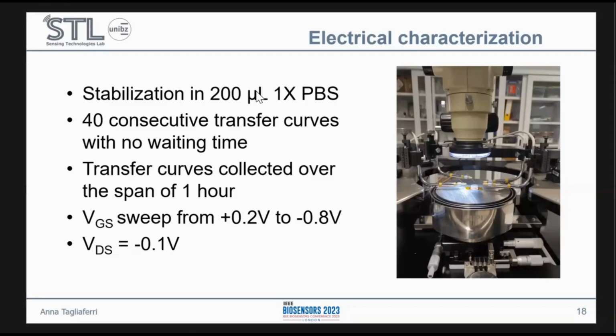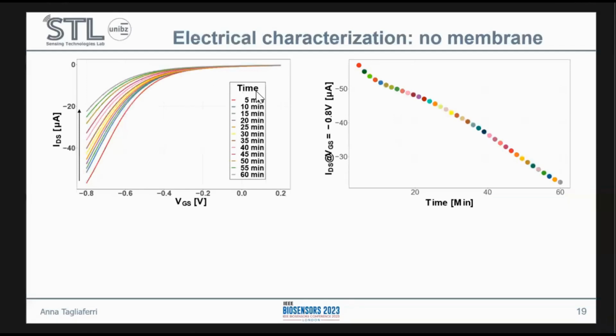We swept the gate voltage from 0.2 volts to minus 0.8 volts, keeping the drain voltage fixed at minus 0.1 volt. The results are seen in these plots here. So this is the result of one of our devices, the transfer curves that we have collected. And what we can see from here is that over time, after each cycle, the current decreases.